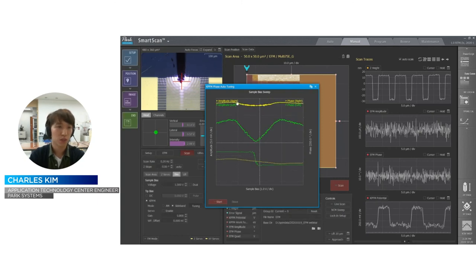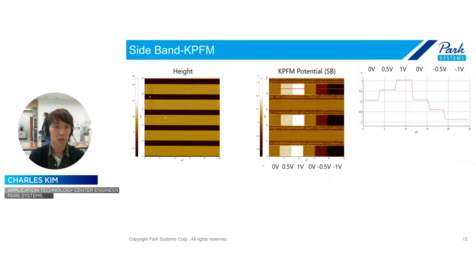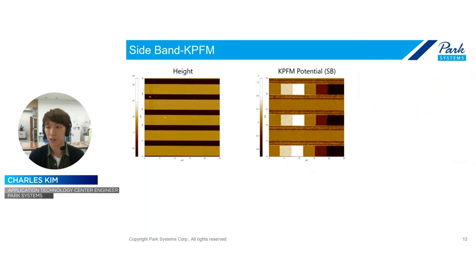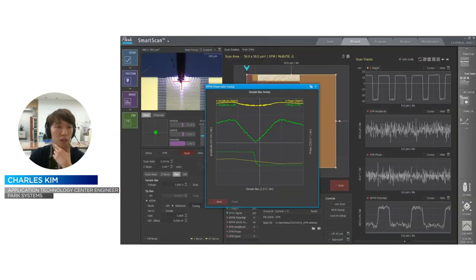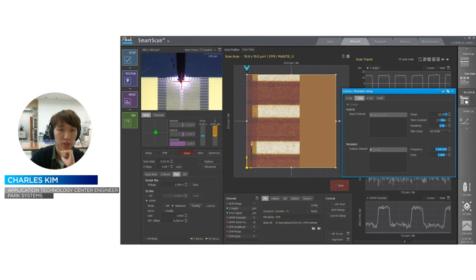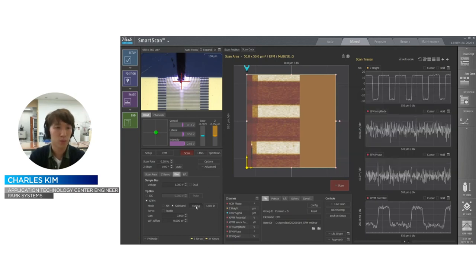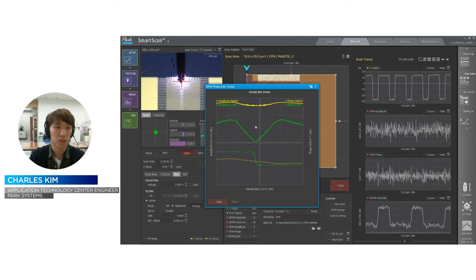Then something different over here is you can see two different colors, which are labeled right and left. Because the sideband KPFM uses the side peaks of the resonance frequency. So for example, if I apply 3 kHz, then there will come a 72.9 plus 3 kHz side peak and a 72.9 minus 3 kHz side peak. So minus means the left and plus means the right. So both peaks' information comes here.